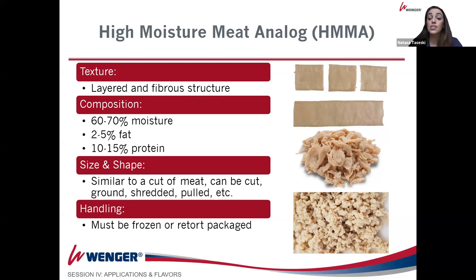Typical composition is 60 to 70% moisture, which is not unlike meat products. Fat content can range between 2 to 5% or maybe completely excluded. Again, fat is typically added for mouthfeel or a certain nutritional profile. And then protein content can vary. It can be as little as 10 to 15% in the finished product that has the high moisture, or it can be up to 25 to 35%. Obviously, depending on what kind of texture you're trying to achieve in the process, that's gonna dictate how much protein you really need to have in the formulation.